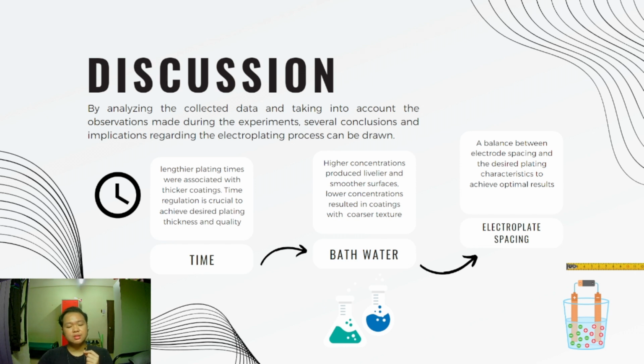The third one is the electroplate spacing between the electrodes. We have done two sessions with constant material and electrolyte use. The spacing is a 2 centimeter and 4 centimeter spacing difference. We found out that the 2 centimeter provided a much thicker coating distribution and heavier mass as compared to the 4 centimeter spacing. However, the 4 centimeter spacing provided a more evenly plated coating in a 30-minute time frame.